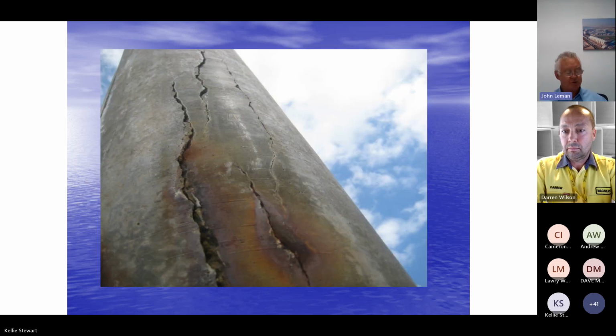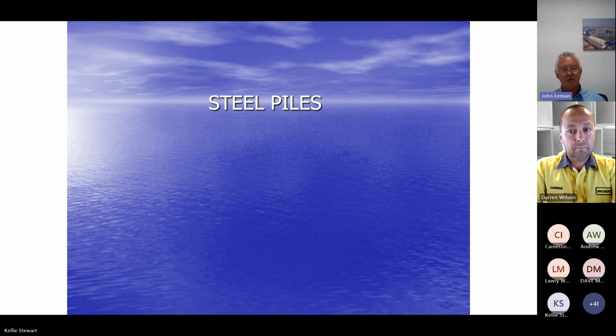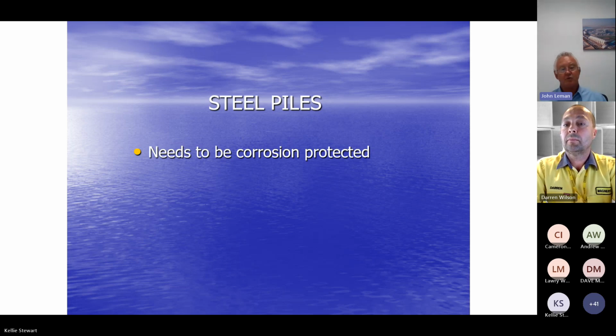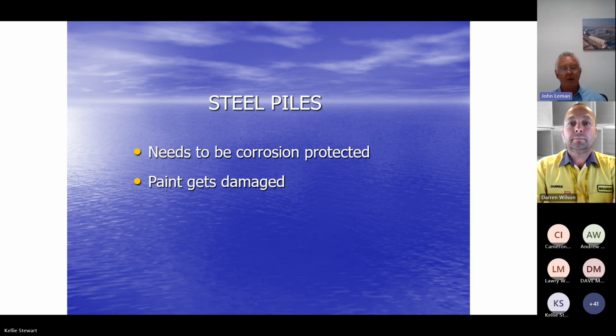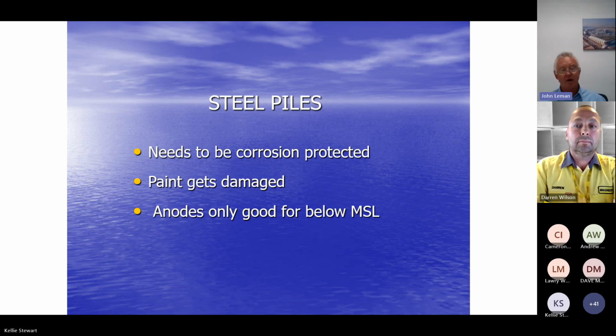Just looking at steel piles, which are the more common option nowadays, obviously you need to corrosion protect the steel piles. In the past, it's been a paint system or high build epoxy. But of course, when the pile drivers are putting these piles in, they're subject to getting damaged, and it's a bit hard to repair a paint system if it's in the tidal zone or under the water. A lot of systems have anodes on them, but of course the anodes only work in a wet medium for cathodic protection. So it's only good for below mean sea level, and we get a lot of corrosion in that upper area, the splash zone and tidal zone.